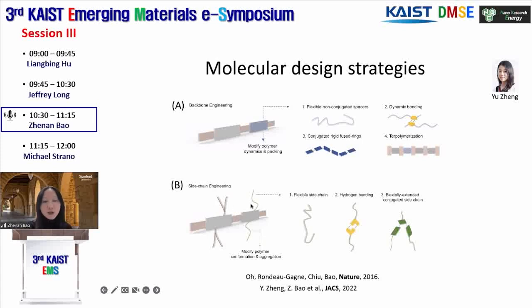Also, we can tune the side chains to introduce disorders. So various these approaches have led to a number of promising designs that provided the minimum decrease in the charge transport level compared to the fully rigid structure and the crystalline structure. There's less than 20% decrease in the charge transport capability, while at the same time introducing the stretchability.